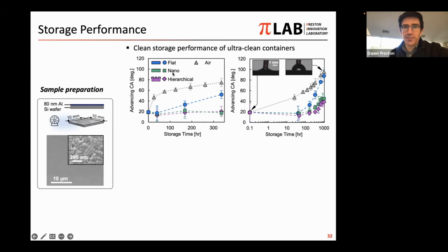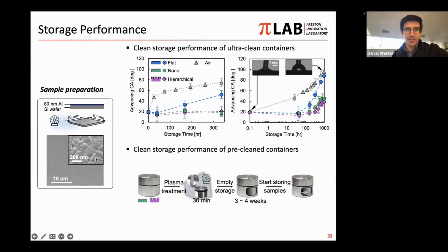And then interestingly, if we start to push to 25 or 50x enhancement in the surface area of this clean container wall, we don't see any increase in contact angle over this period of study here. In this case, the samples are also aluminum, same material as the container itself, and nominally flat. We wanted to see whether or not this approach also would allow us to generate ultra clean, high surface area containers that could maybe be produced in bulk, saved for later, or shipped around the country as a product.